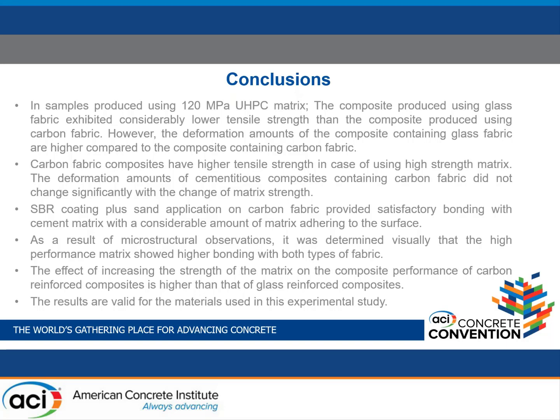Carbon fabric composites have higher tensile strength in case of using high strength matrix. The deformation amount of cementitious composites containing carbon fabric did not change significantly with the change of matrix strength. SBR coating plus sand application on carbon fabric provided satisfactory bonding with cement matrix, with a considerable amount of matrix adhering to the surface.